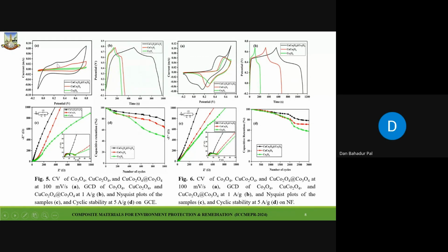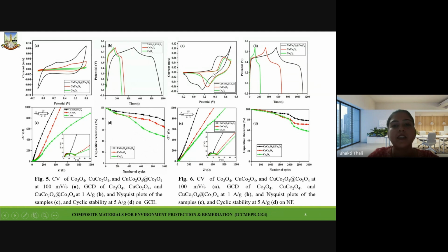There were slight redox peaks seen for glassy carbon, but in the case of nickel foam, proper evident oxidation and reduction peaks were seen. Also, we can see that the composite showed better oxidation and reduction, suggesting good supercapacitive performance, that is pseudo-capacitive. For the GCD, Figures 5B and 6B are the comparative GCD curves, in which also we can see the composite was maximum compared to the other two materials.